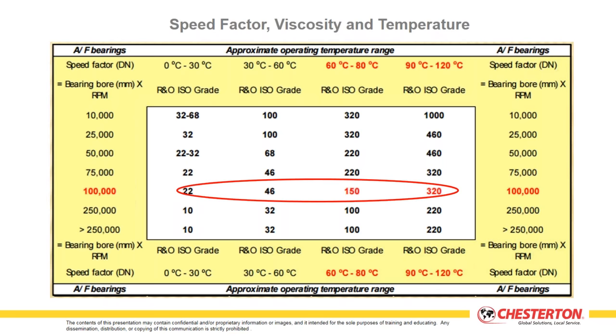But if I take that piece of equipment off the shelf in my warehouse, and I now put it in an application where I operate at 90 degrees Celsius, you have to make a viscosity adjustment to use an ISO 320 based oil to temperature compensate to maintain the same thickness at a higher temperature. So as a building block, do we temperature compensate and choose a viscosity based upon our operating temperature? Or do we just use what's stated in the OEM manual for the piece of equipment?